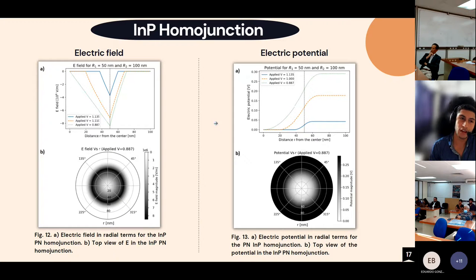Like in the heterojunction case, we show in this slide the electric field and the electric potential. It's important to say that in this case, the electric field is continuous between the two materials. This fact is because the dielectric constant is equal for the homojunction. So we select for figure B the applied voltage equal to the critical voltage, 0.887 volts, and we get the magnitude of the electric field in the indium phosphide homojunction in radial terms of the device.